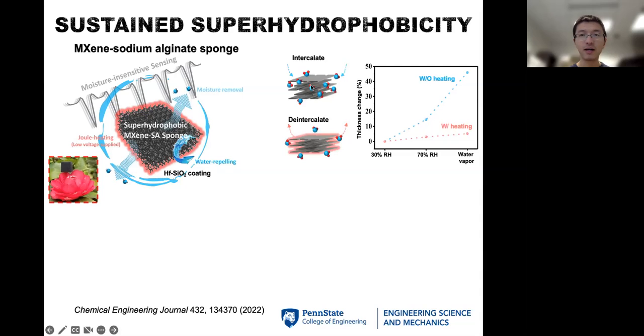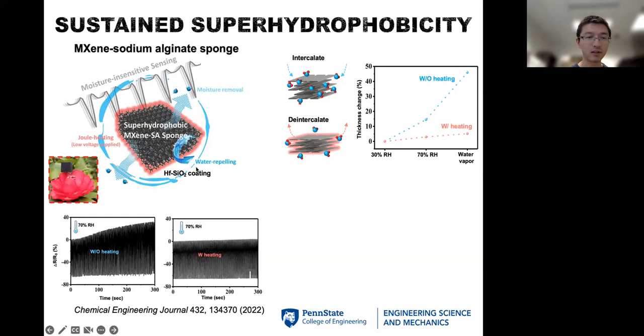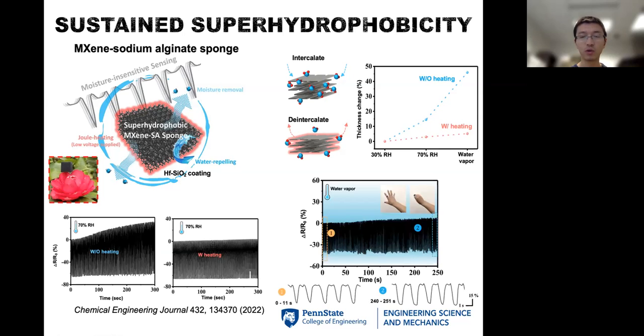So the MXene layer, without heating, will just accumulate a lot of water molecules, and then the thickness will increase. But if you increase the temperature through the Joule heating, it can maintain a really robust structure. From that direct comparison, at a relative humidity of 70%, if you don't have heating, it's going to drift quite a lot in terms of the signal we measure. But if you have heating, it's much more robust, and we can do humidity and water moisture insensitive detection of the motion. That's really something more useful in all weather conditions where people can engage in different activities.